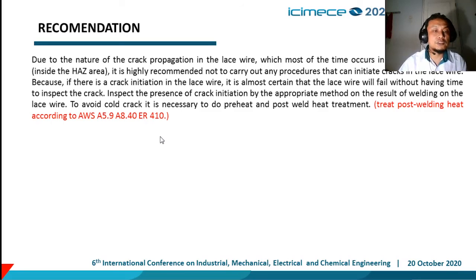Recommendation: due to the nature of crack propagation in the lace wire, which most of the time occurs as an embedded crack inside the heat affected zone, it is highly recommended not to carry out any procedure that can initiate a crack in the lace wire. Because if there is crack initiation in the lace wire, it is almost certain that the lace wire will fail without having time to inspect the crack.